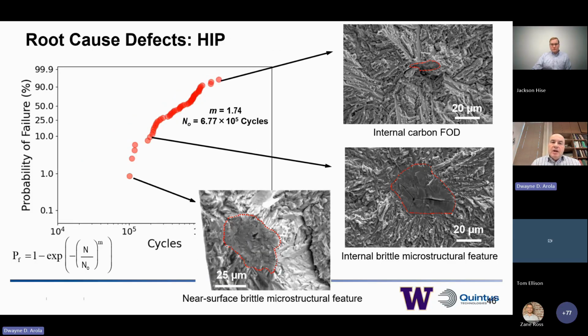if we do the same now for the HIP treatment, what we saw for the stress relief condition is a very straight line for that Weibull distribution. In this case now for the HIP treatment, we see a little bit of bumps and curves here, which really means typically that there's more than a couple contributions of factors to the fatigue life distribution.